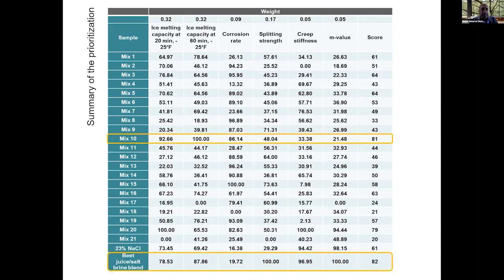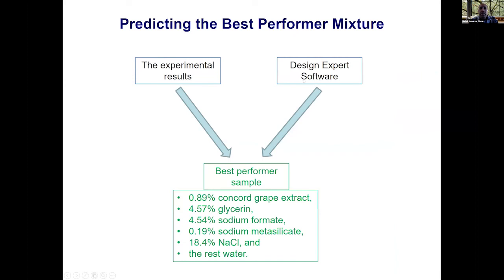So again, using a similar process, we prioritized these deicers. Among them, mix 10 and beet juice blend. This beet juice is different from beet juice extract that we use. It is a commercially available deicer with a high concentration of beet juice byproduct. So these two mixtures had the best scores. So we used the experimental results and design expert software to predict the best performer sample, that has better properties than beet juice blend and also less impact on the environment.